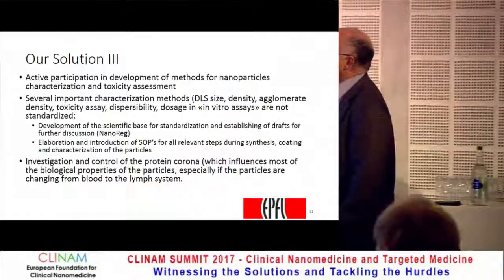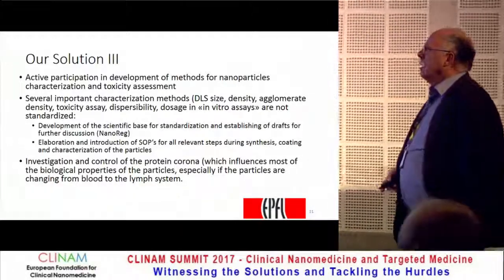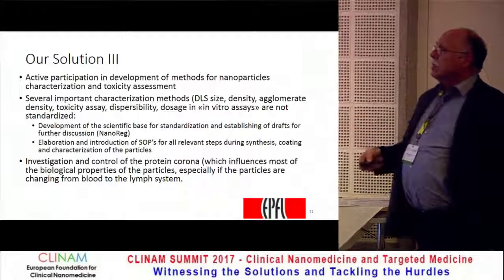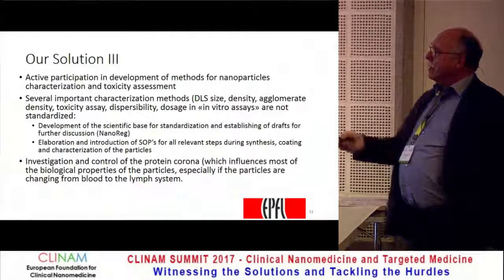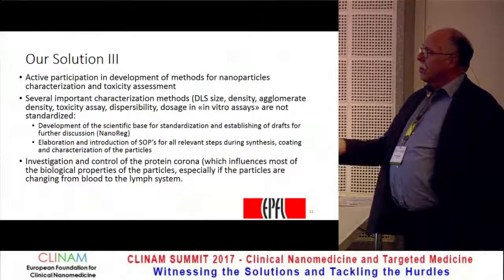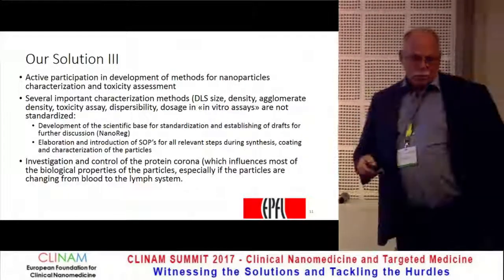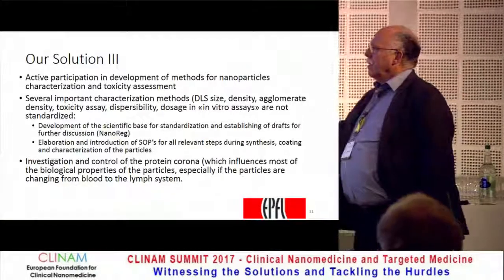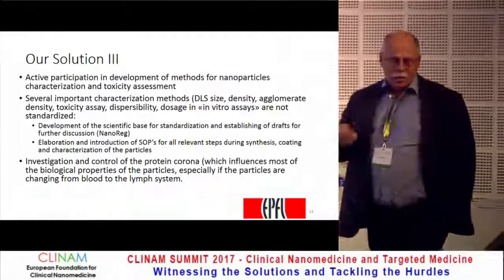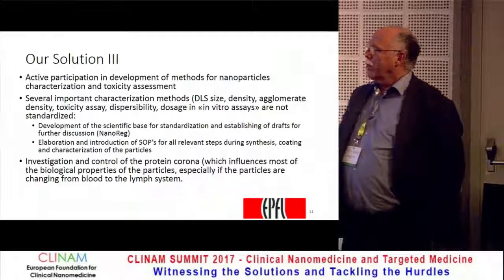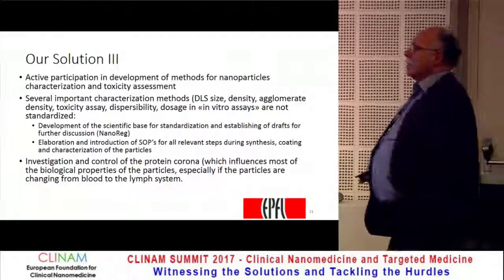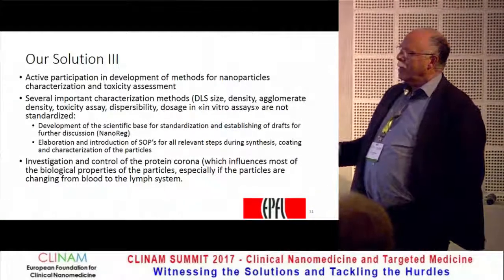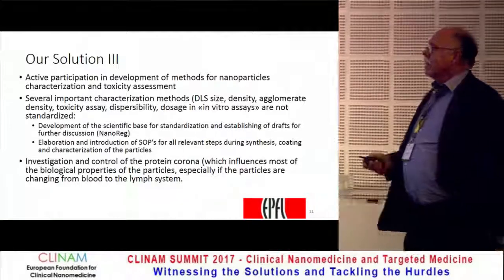Control of the protein corona is very important, because if you don't control it, you cannot control toxicity, biodistribution, and other things. Controlling the protein corona means you have to control the coating and how you administer the particle to the body and to the right system. For example, if you go into the blood or into the lymph system, you need a different coating, because then you have a different protein corona on the surface and therefore different behavior in the body. You have to know the application you are developing the particle for.